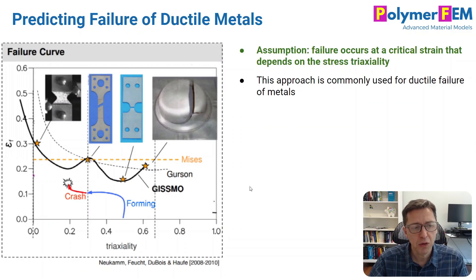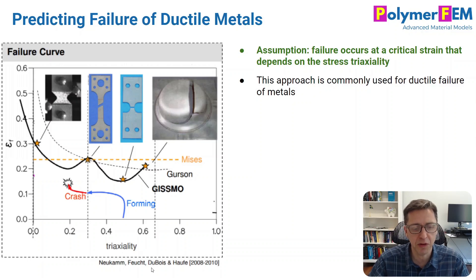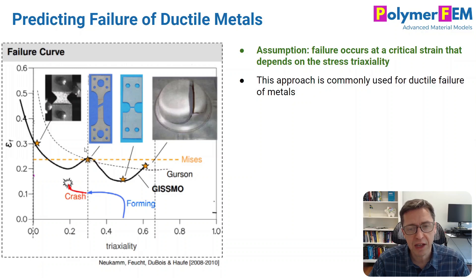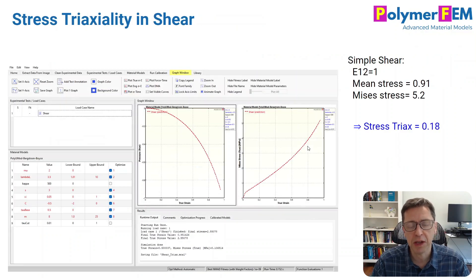What they do in that case is define a failure strain and make that failure strain depend on the stress triaxiality in some way. Here's a graph grabbed from a paper by Dubois and co-workers showing the critical strain as a function of triaxiality — and this is for metal, of course, not for a polymer. But this approach can actually be used also for polymers, and it's used relatively commonly in the automotive industry. I'm going to show you a little bit about how that works today for thermoplastics.